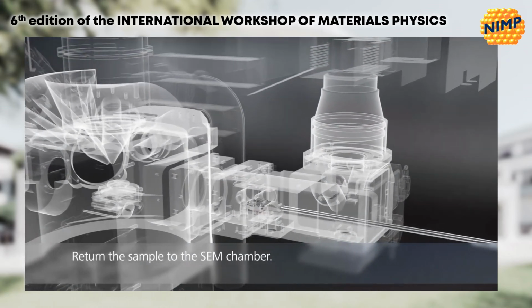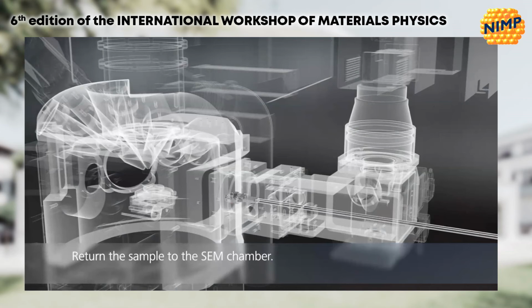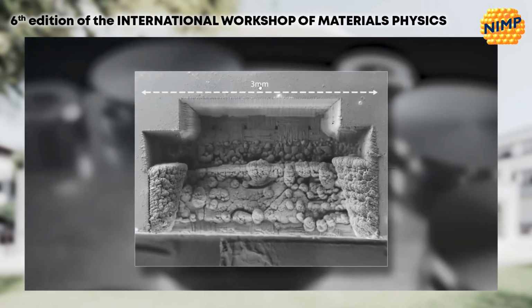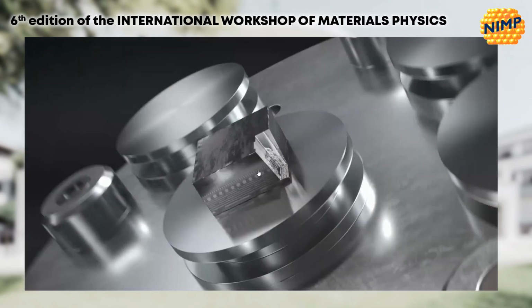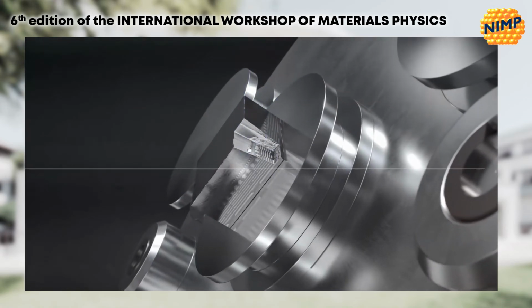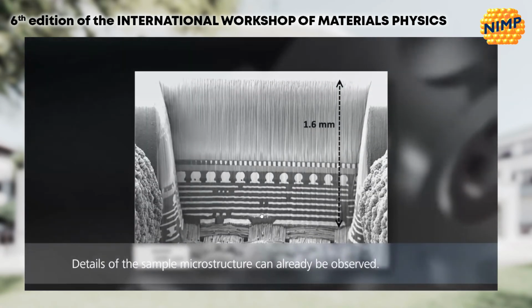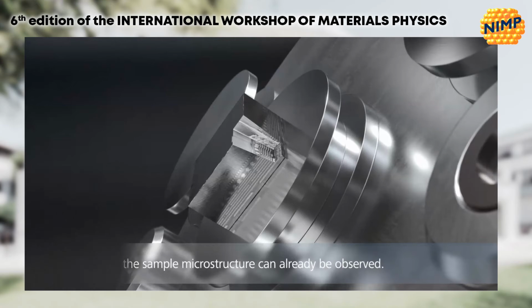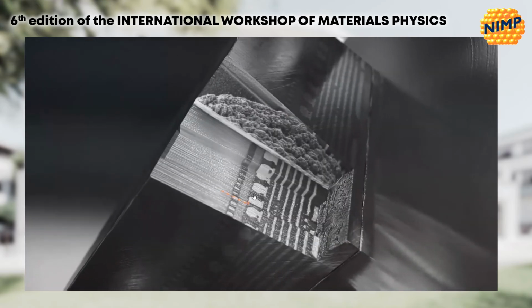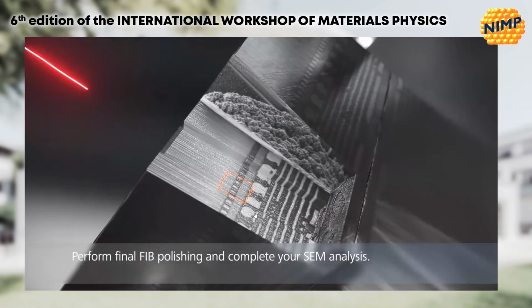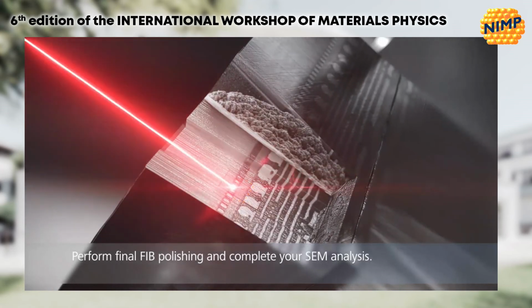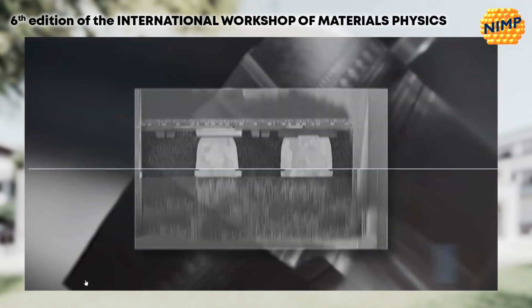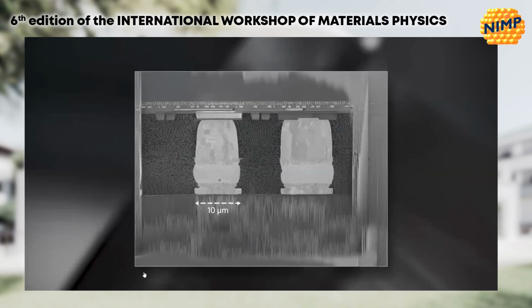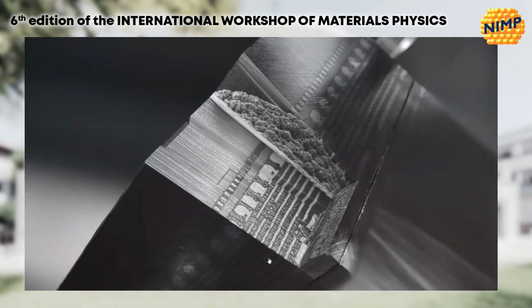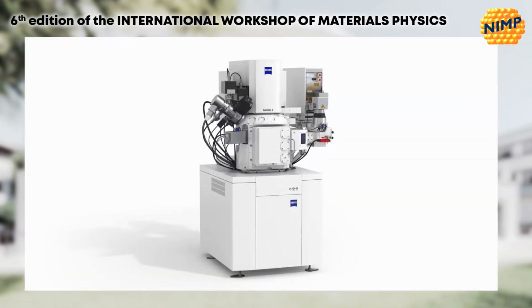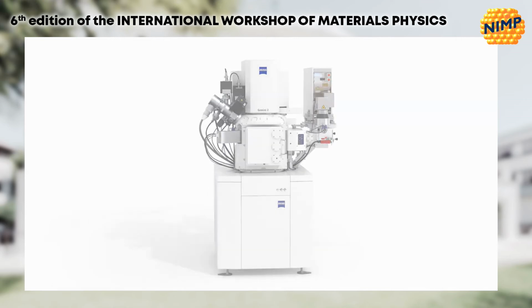Moving back to the dual beam system, you see the size, millimeter thickness. We are performing now the final polishing with the gallium FIB, and finally we have our area of interest where we perform our high resolution images, and then you get very quickly this final result. And this is a nice example of how a 3D correlation works.